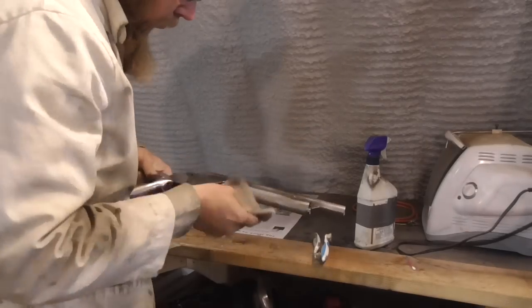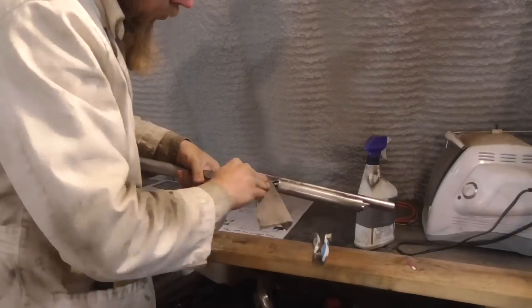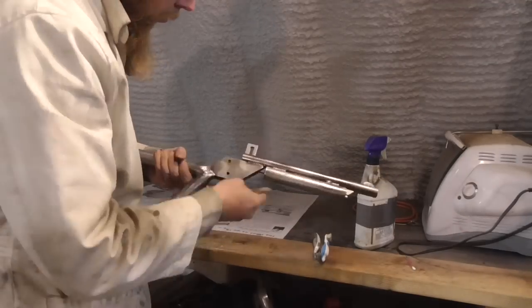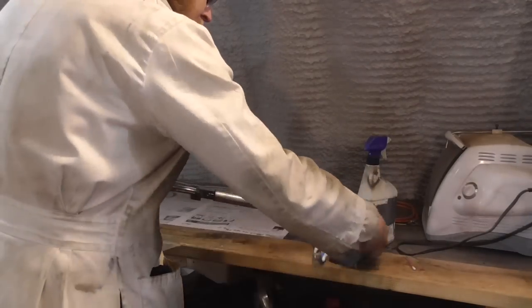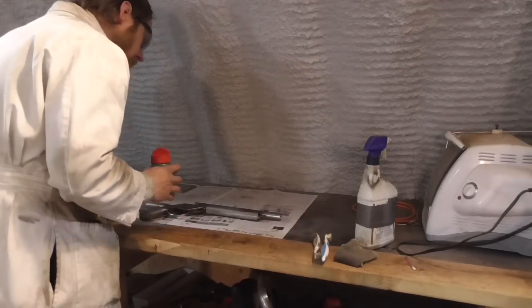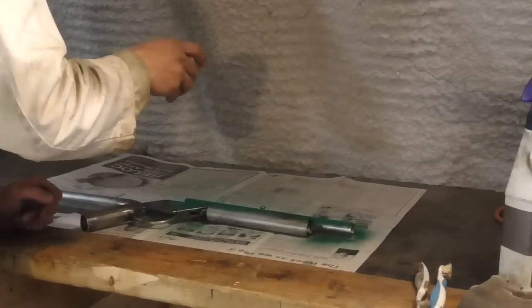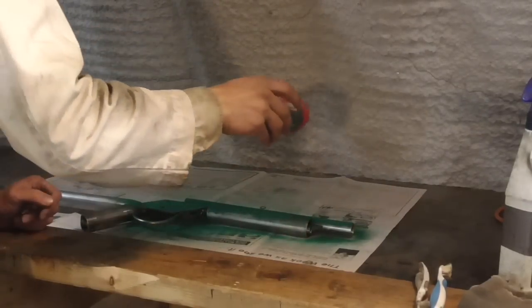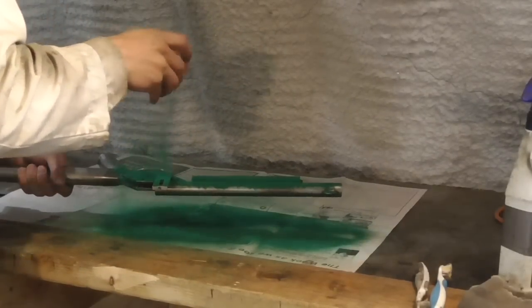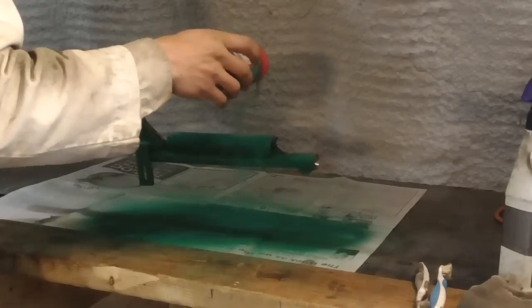For a metal finish I decided to powder coat the muzzleloader in a dark forest green color. Since I don't have professional powder coating equipment, I used the WD-40 method. This consists of cleaning the metal and wiping it down with a rag moistened with WD-40 to deposit a thin film over the entire surface. The powder is then sprinkled generously onto the metal using a repurposed spice container with a shaker top, and lightly tapping the part shakes loose any excess, leaving a fairly uniform layer of powder adhering to the WD-40 film.